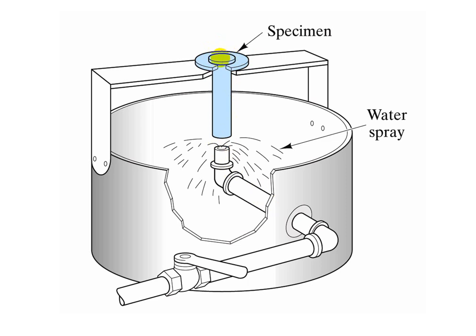So this specimen, regardless of the actual alloying elements, as long as it's a ferrous alloy, it has relatively the same thermal conductivity. So the same cooling rate regime applies to the distance from Jominy head. The further we go in this direction, obviously the cooling rate decreases. Here is the highest cooling rate, at this end is the lowest cooling rate.